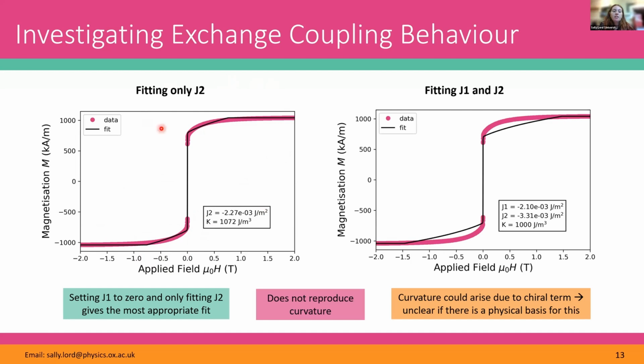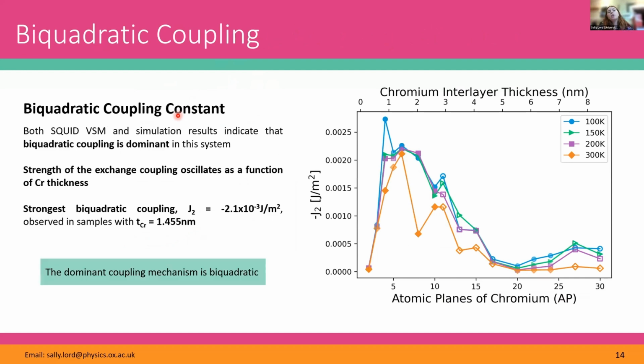So anyway, we ran this fitting program for all the samples, and we extracted the biquadratic coupling constant for all of the samples. And here we plotted the biquadratic coupling constant J2 versus the chromium thickness. What you can see is that the strength of the exchange coupling oscillates as a function of the chromium thickness. There are sort of two periods, and you have a peak in the exchange coupling around 1.45 nanometers. And there's a large range of chromium thicknesses where the biquadratic coupling strength is large.